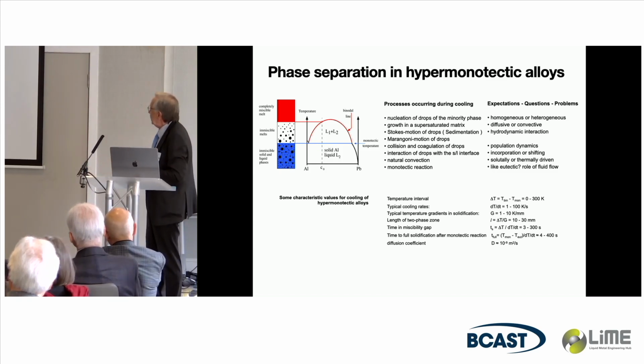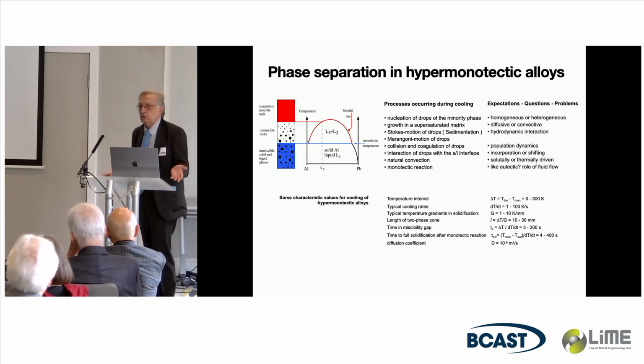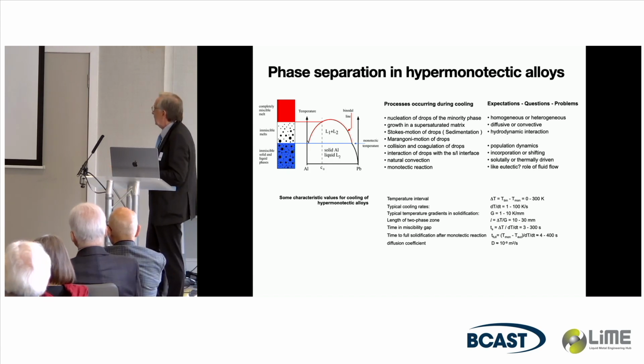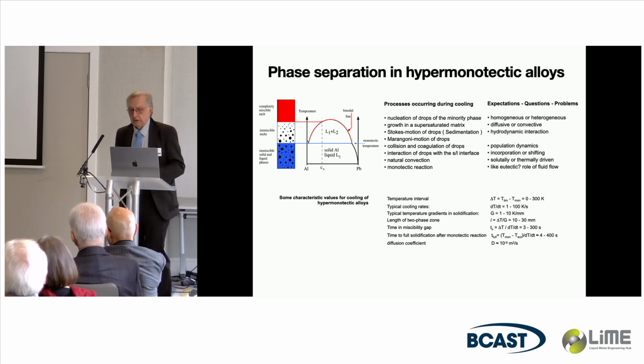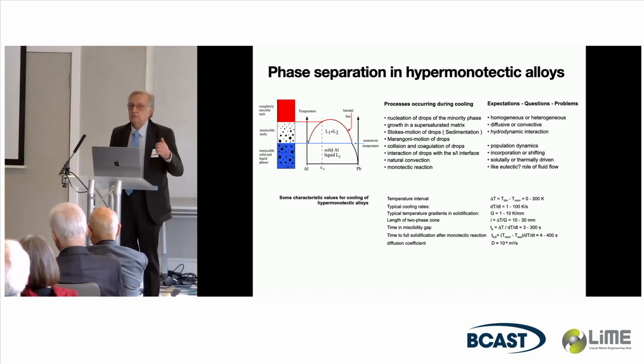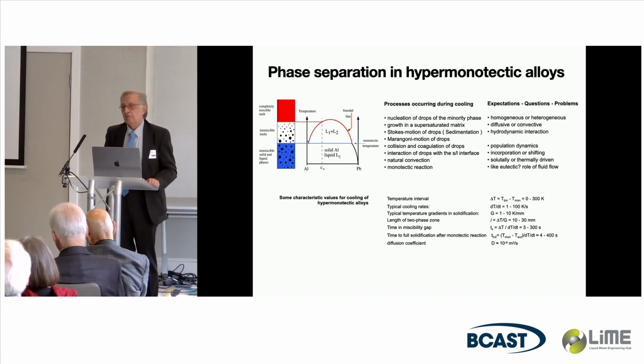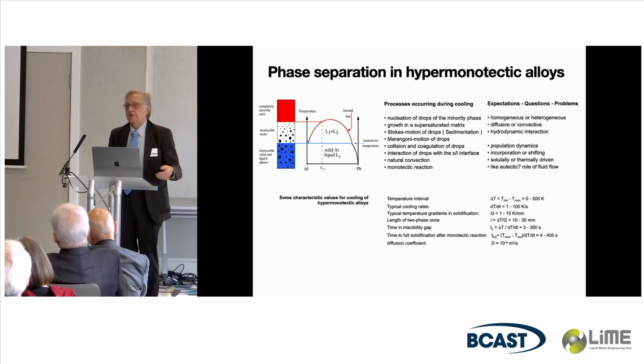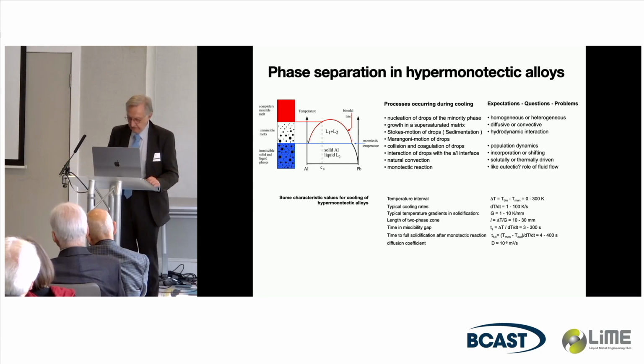That's complicated. The length of this two-phase zone is of the order of a few millimeters, 10 to 30 millimeters, depending on the temperature gradient. And the time in the miscibility gap, as I said, is around a few hundred seconds. Diffusion rate in liquid is fortunately fast enough, 10 to the minus 9 square meters per second. So diffusion and growth by that occurs rapidly compared to, let's say, a solid state.